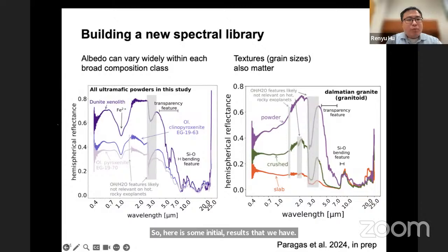We found that the albedo of a rock type can vary widely within each broad composition class. So for instance, on the left, I'm showing 3 kinds of ultramafic material, and they have very different reflectance in the visible light. And we also found that the albedo can vary greatly with the grain size or the texture. So on the right, I'm showing you a granite, but between the powder or crushed or slab surface, their reflectance could also change substantially.